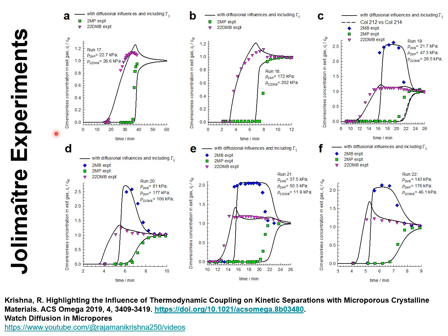To model the breakthrough experiments published by Jolimaitre, we need to take proper account of both adsorption and diffusion. And for modeling of diffusion inside the micropores, there is a need to incorporate the Maxwell-Stefan diffusion formulation, in which due account is taken of thermodynamic coupling effects.